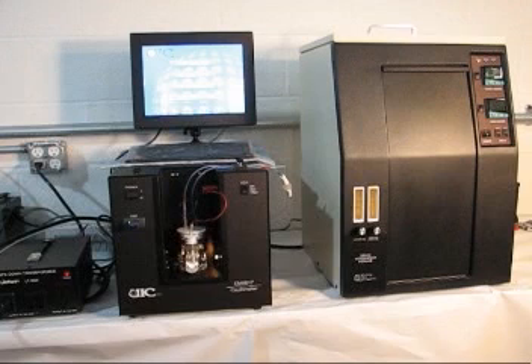A check valve must be installed between the furnace and the coulometer to prevent the siphoning of coulometer solution into the furnace. Whenever the furnace temperature is reduced or the furnace is turned off, disconnect the furnace carrier gas outlet line from the coulometer cell. Switch off the CM220 autosampler furnace, but leave the carrier gas flowing for another 5 to 10 minutes and do not open the furnace until it is cooled off, or else the combustion tube might break.